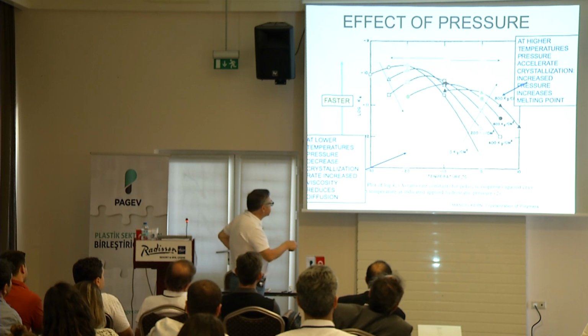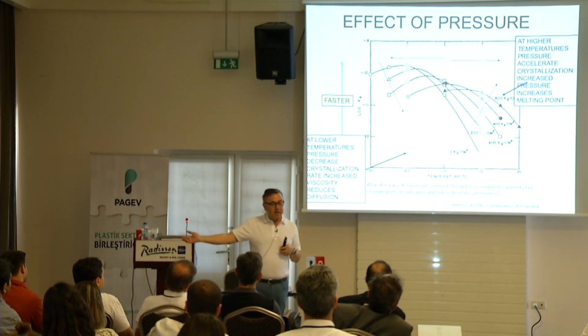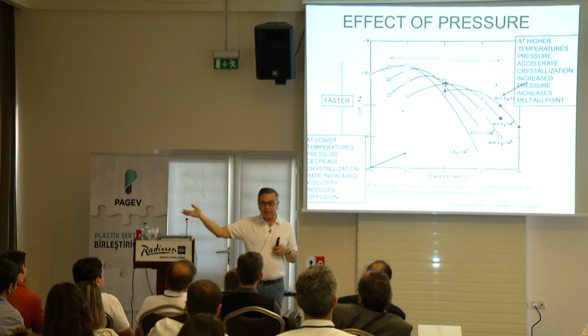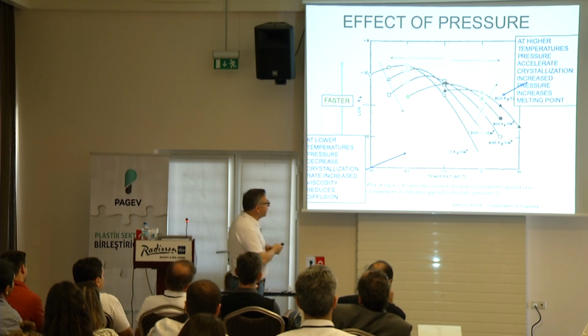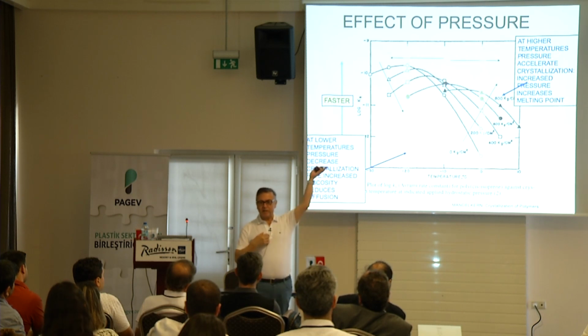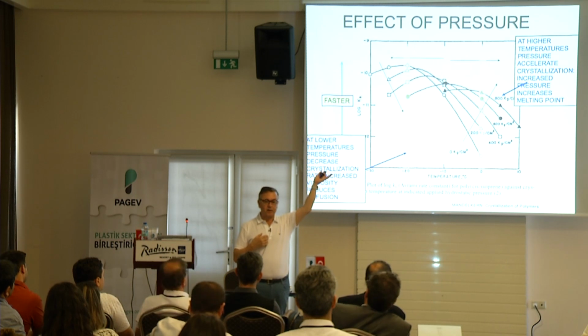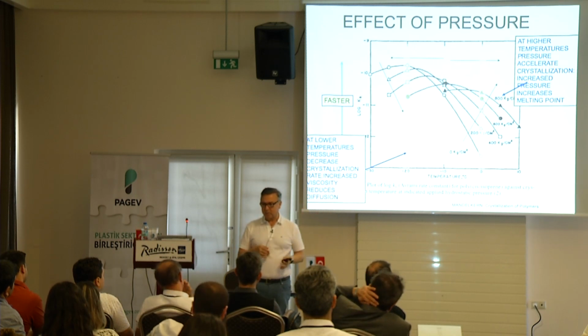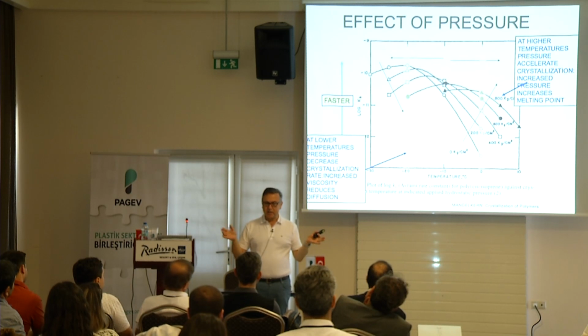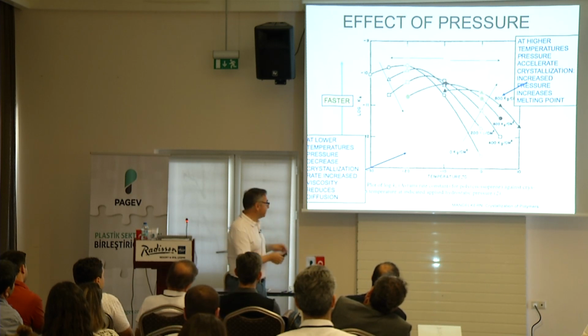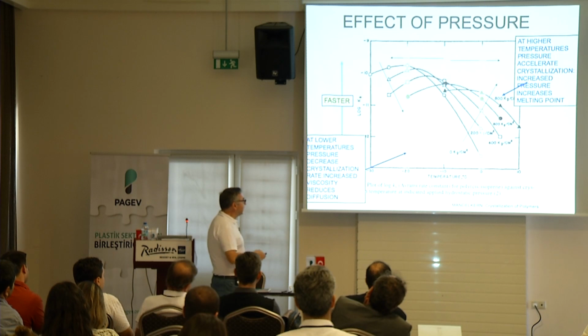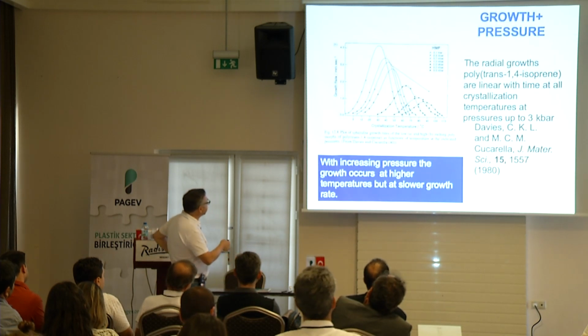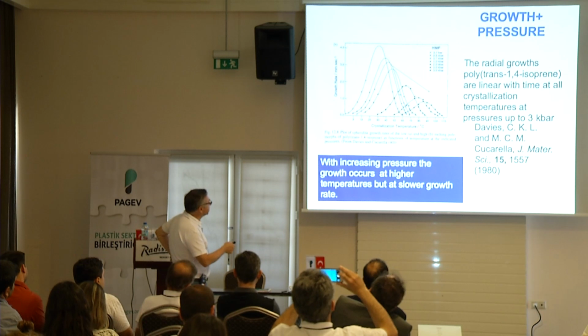Because at lower temperatures, remember, the viscosity is so dramatically affected by the pressure. It dramatically slows down the crystallization because the viscosity dominates. But at higher temperatures, it's the other effect. The melting point increases, the material thinks that it is at a lower temperature and crystallizes faster. Complex situation, isn't it? So it depends on where you are. Opposite effect. In between, I have a neutral territory. That's why you get this kind of growth rate behavior on crystallization at different pressures.